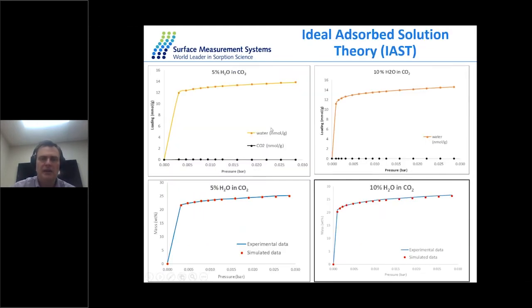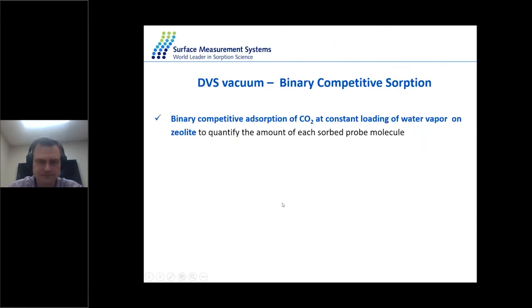So now we can employ the ideal adsorbed solution theory to see how much CO2 is absorbed in the presence of 5 and 10% of water. As you would expect, for 13X, the absorption is dominated by the water, so the CO2 absorption is negligible or non-existent. But if I plot these two values together against my experimental data, the solid blue line and the simulated dotted red line, we can see that we have good agreement for 5% and 10% of water.